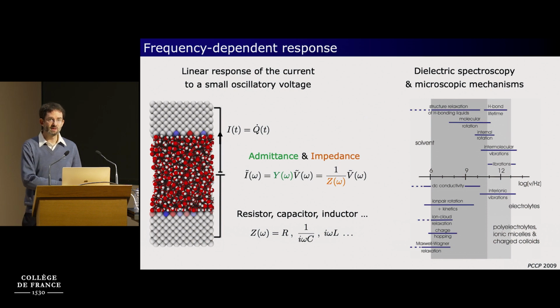Very recently, we extended this linear response with fluctuation dissipation for the capacitance to the frequency-dependent response. So this corresponds to the linear response of the current, which is a derivative of the electrode charge, to a small oscillatory voltage applied between the two electrodes. And if you remember your lectures in electronics, this response is characterized by the frequency-dependent admittance, or its inverse, the frequency-dependent impedance, which is usually a complex number. And for a resistor, it's independent of frequency, it's just a resistance. So the impedance is just a resistance. For a capacitor, it's 1 over i omega times the capacitance, and so on.